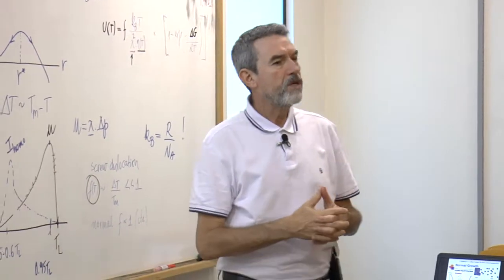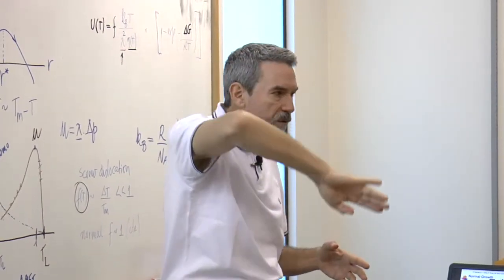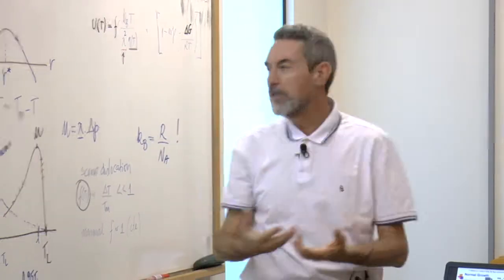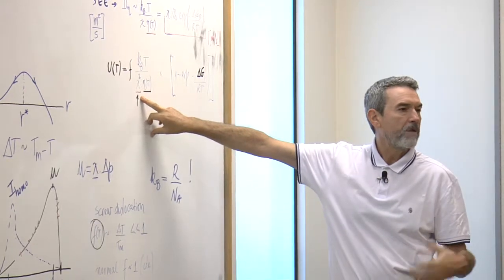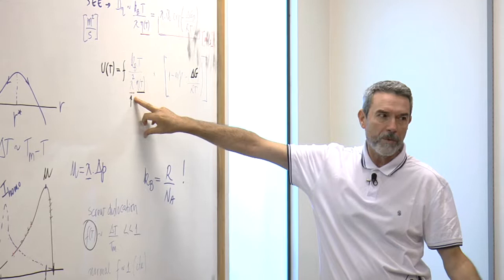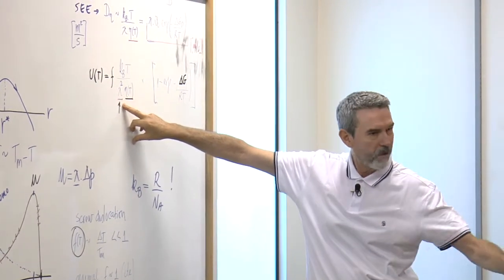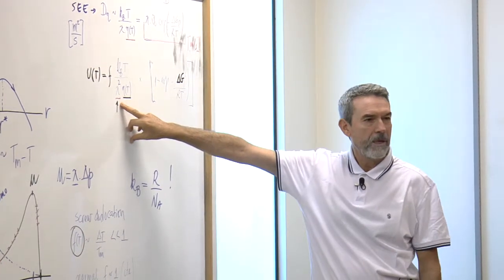You have a good result if you're able to fit the temperature dependence of the growth rates and get a resulting value of lambda of about 1, 2, 3 angstroms, maybe 5 angstroms, not 1 kilometer. If it's 1 mile, 1 kilometer, you're off. It has to be a few angstroms.